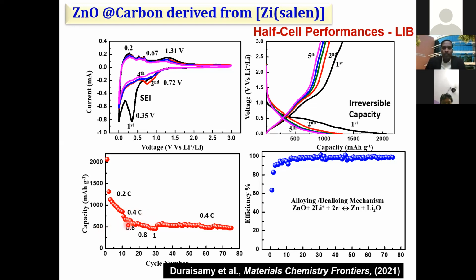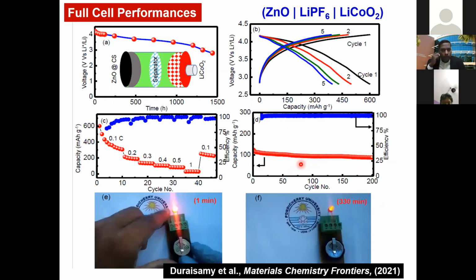Amazing. Zinc oxide is supposed to have very poor electrochemistry, but you can see that it reacts with the lithium and gets converted into zinc and back and forth. Alloying, de-alloying mechanism, what we call, and the Coulombic efficiency in the extended cycle life is very high. So since it showed 500 mAh as the discharge capacity, why not go for the full cell performance?